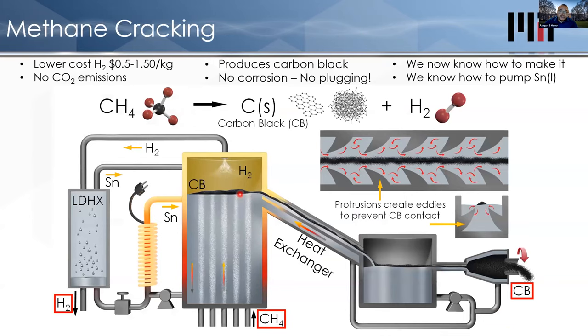One other thing we're working on using liquid metal is another approach we just got funding for, which is methane cracking. So this is making hydrogen without making CO2. You take in methane, you bubble it up through something like liquid tin. Tin has no chemical interaction with carbon or hydrogen, so it's completely inert. Inside the bubbles, the methane decomposes, turns into hydrogen, and you get a solid carbon particle that floats on the surface of the tin. Then because we can pump liquid tin at extremely high temperatures, we can move the carbon out and do the separations and lots of heat recuperation to make this efficient. So we're also about to start building this prototype in my lab.